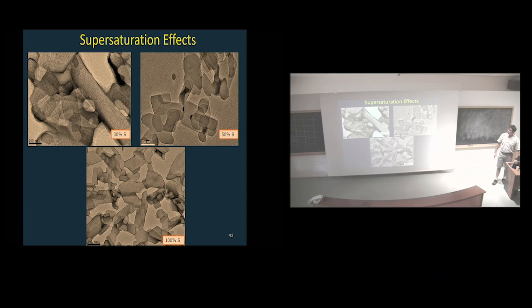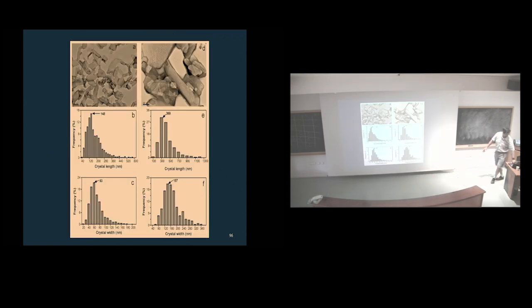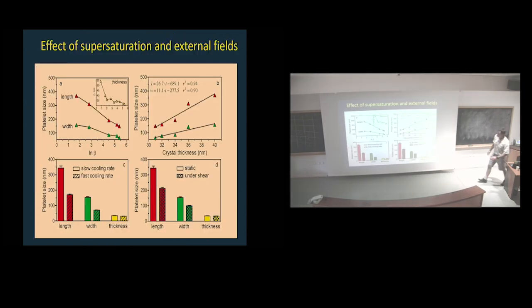So these things are super sensitive to external fields. If you have a higher supersaturation, like 100%, or you dilute it with oil, you see gigantic changes in the size of these things, just for you to see. If you have a greater supersaturation, you can change things from almost 400 nanometers to like 200, it changes a lot. And so does the width.